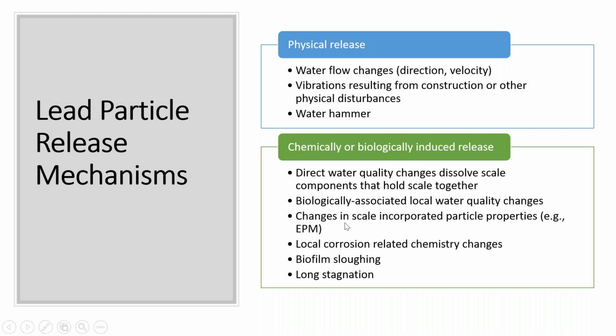resulting releases of particles. It could be biologically associated releases as well. Maybe microbiology is related to local water quality changes in the scale that could result in some sloughing off, and the biofilm itself gets sloughed off, and particles could be incorporated into that. Changes in scale incorporated particle properties as well. So making a change in water chemistry could affect the nature of the particles that are already in the scale and cause them to come off in some way. Maybe it's charge repulsion, for example. Local corrosion related water quality changes, biofilm sloughing I mentioned, and long stagnation can result in changes in local water chemistry. And I'm sure there are others that I've forgotten here.